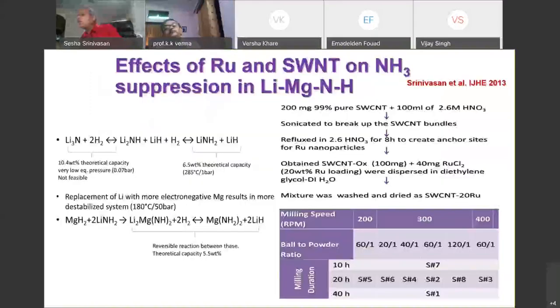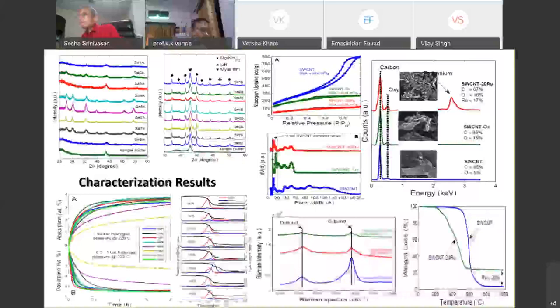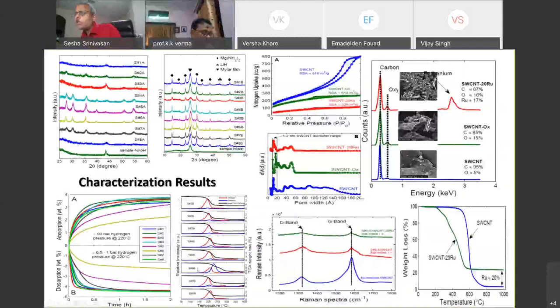One of the materials we looked into, sometimes these materials may have two gases released. One is hydrogen and the second one is ammonia. Ammonia is not good for fuel cells because it will poison the membrane, whereas hydrogen is good. We wanted to suppress the ammonia by doing some kind of optimization. What I want to show is that we tried different material synthesis and optimization. Look at the fourth figure on the bottom from the left. You will see the hydrogen to ammonia peak is going down.